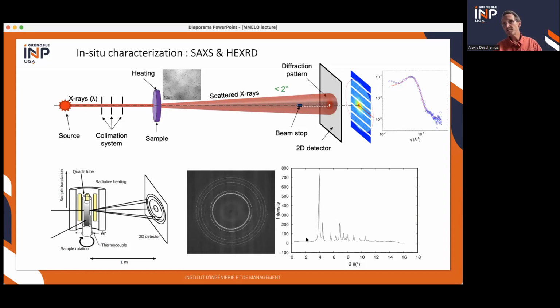And for more allotropic transformations, considering a relatively high volume fraction and not too small sizes for the different phases, it's even simpler in principle: it is to do bulk diffraction at high energy. So high energy would be something like 100 keV, available mostly at synchrotrons. Which makes it possible to have really a bulk sample, including on relatively heavy materials such as steel or nickel, and collect quite a number of diffraction rings that give you powder diffraction profiles that you can interpret in terms of phase fractions or lattice parameter.